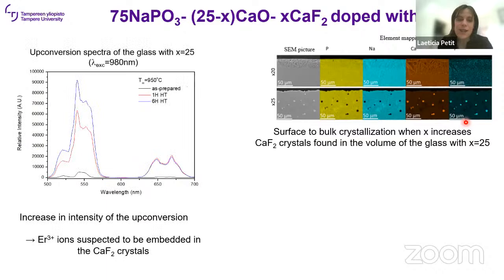So we look at the upconversion spectra of this glass, in black prior to and after heat treatment, and we can see a huge increase in the intensity of the upconversion, indicating that the erbium ions are actually entering inside the calcium fluoride crystal. So this is a very promising glass for this type of application.